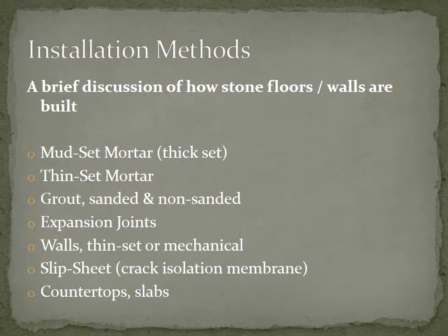Mud set mortar is what they typically call thick set installation, where there is a mud. It can either be a wet mud or a dry pack mud. The correct way is with a dry pack mud, which is 1 to 3 approximately sand and cement mixed with very little water, so it's still relatively fluffy. The test, if it's got enough water in it, is to grab a handful of this dry pack, they call it, and clench it with your hand. And if you can open your hand and it stays together, then that means it's good. That's what you want. You want to see enough moisture in there for it to hold together.